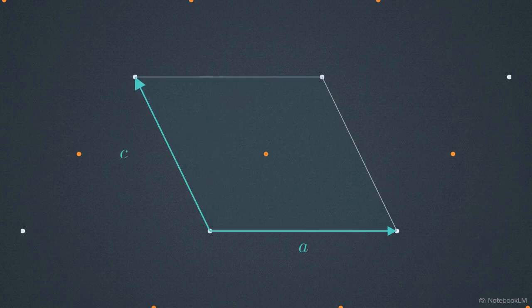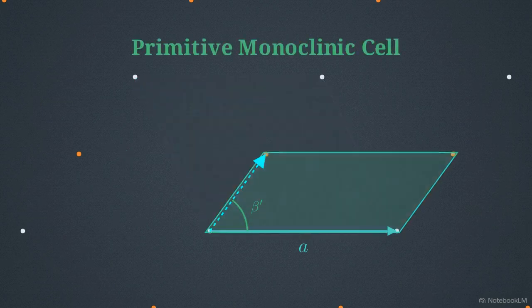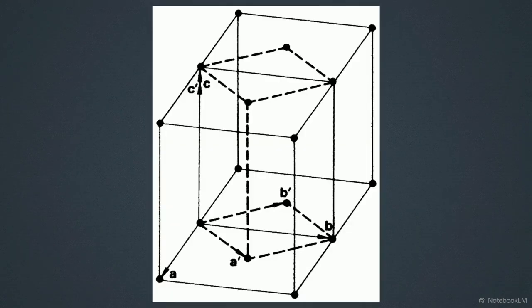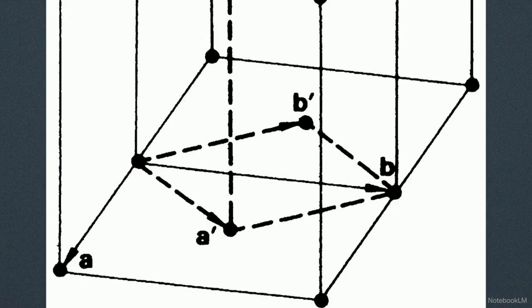bounding box. This specific transformation is valid. The monoclinic system requires the angle beta to be oblique, and our new angle, beta', meets that requirement. Therefore, a B-centered monoclinic cell reduces perfectly to a primitive one. This demonstrates the exact same reduction test on a C-centered monoclinic cell. Look closely at the resulting base vectors.